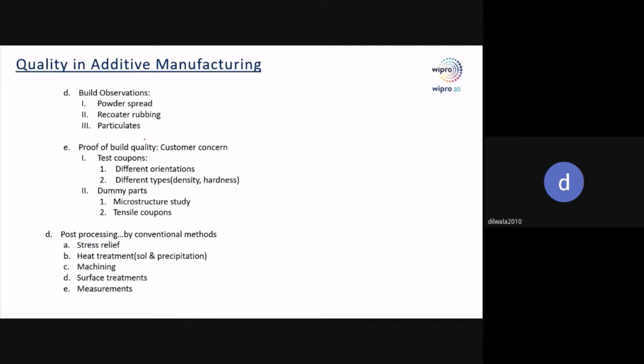Then comes proof of the build. Proof of the build quality is something customers are generally concerned about. They would say, your build plate looks all right, but how do you ensure quality? Many times they say, have multiple test coupons, in different orientations. Some may be horizontal, some vertical, some inclined at 45 degrees, and some square coupons to test the density and hardness of the parts printed from that build. Then they also tell us to check the fill was proper and all the requirements.